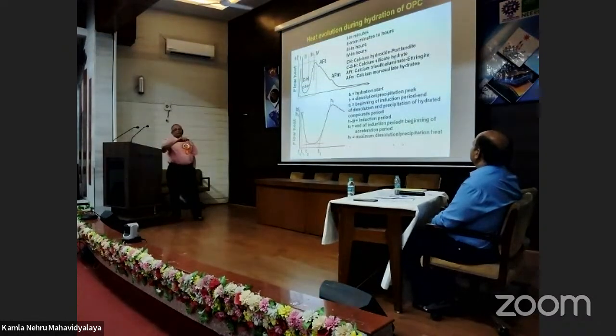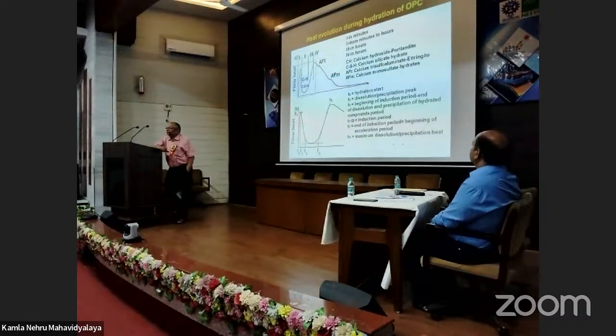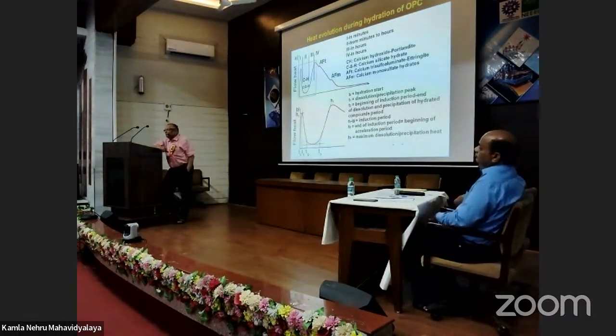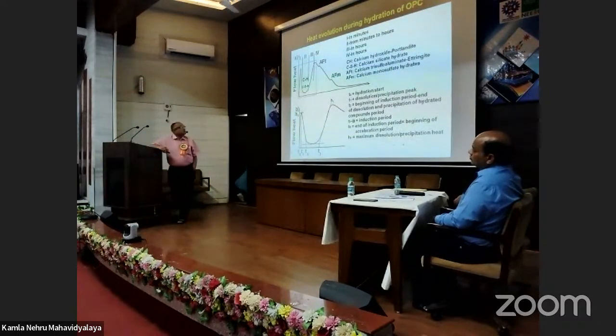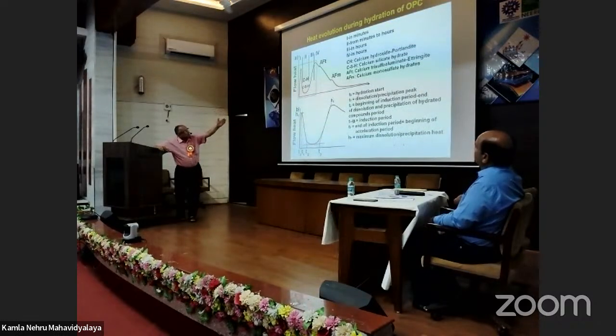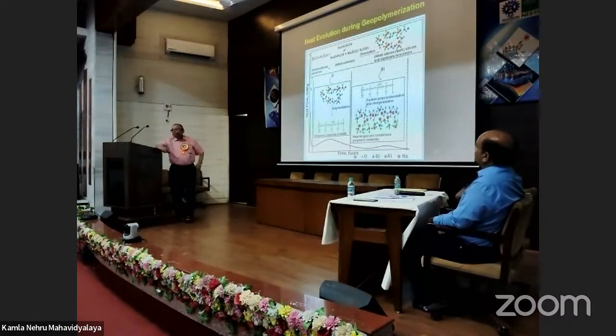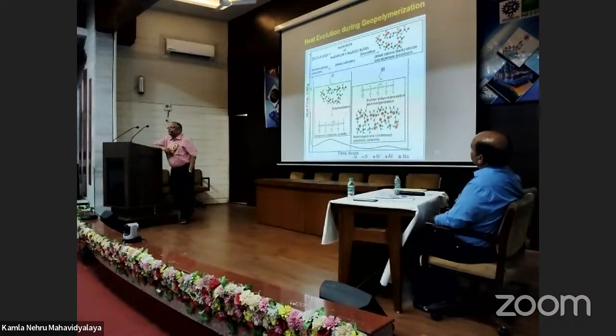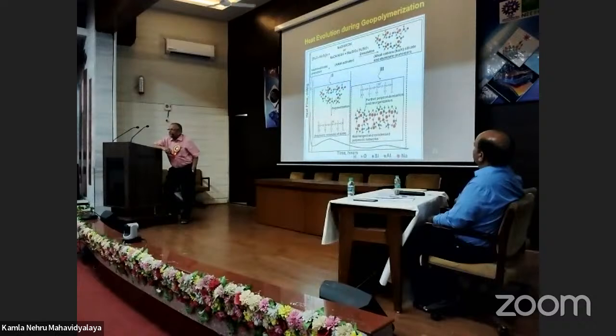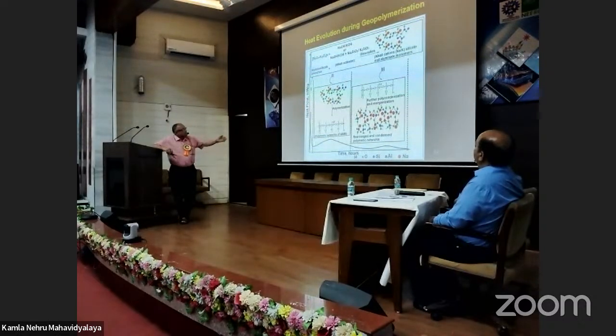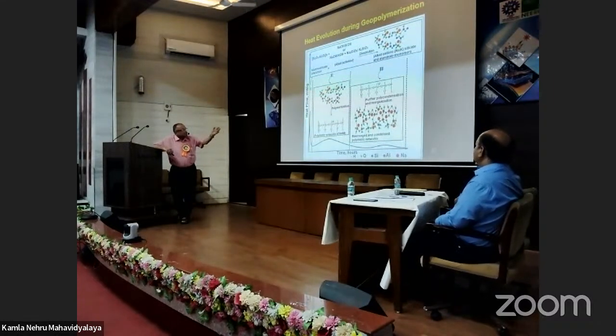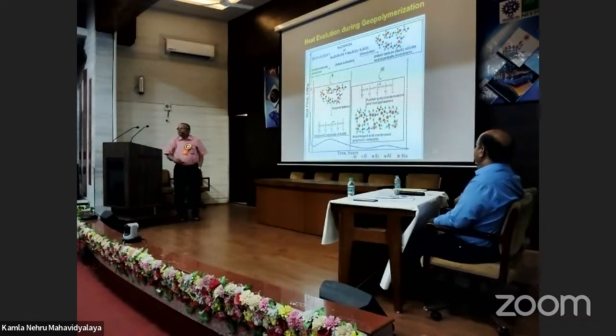a building. Now here, when we add water to Portland cement, heat evolution takes place. Hydration of cement is a highly exothermic process, and you can measure it with the calorimeter, and the different steps involved during the hydration, you see that 1, 2, 3, 4, or 5, we can say in the first, it is in minutes, from second minutes to hour, third stage in hours, fourth in hours, different phases are formed here. Now, if we take the case of geopolymerization, it is also an exothermic process, but it is not as complicated as the hydration of Portland cement. So, in the first phase, polymerization takes place, and then in the second phase, further polycondensation, giving you finally the